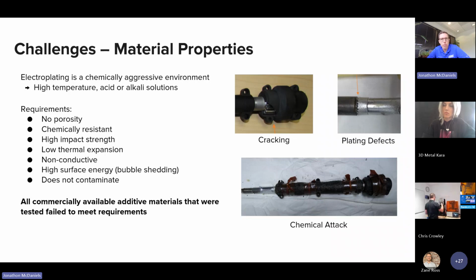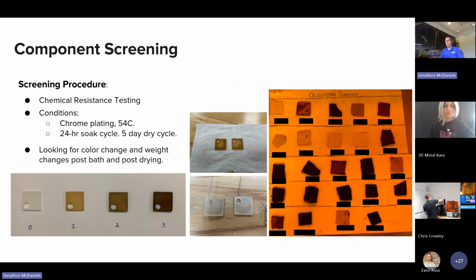In our early stage testing, we found that all commercially available additive materials that we tested did not meet these requirements. So we had to go out and create our own. Our initial work for this development was to screen a large number of formula candidates for chemical resistance performance before we even got it into a printer. Once we had printable formulations, we could get cubes for testing, but we put them in the chrome bath, 24-hour soaks, 5-day dries, looking for color changes, evidence of leaching, and weight changes, so that we could screen out the most promising candidates.